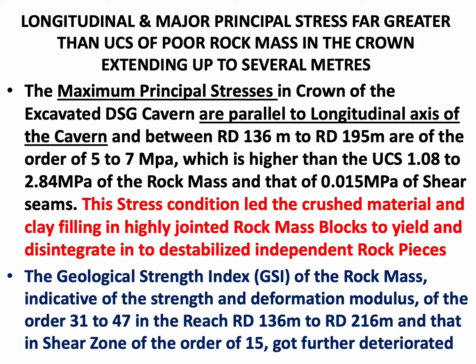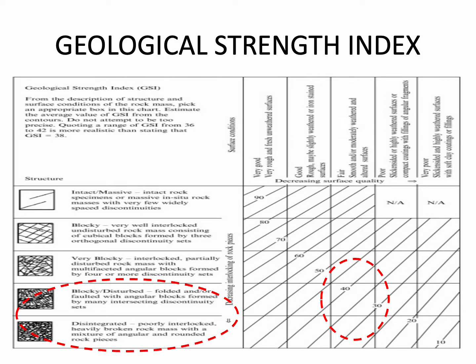The geological strength index of the rock mass, indicative of the strength and deformation modulus, is of the order of 31 to 47 in the reach 136 to 216 meter, and that in the shear zone of the order of 15 must have got further deteriorated. These are the original geological strength index considered, but with the stress conditions that we are seeing, of 5 to 7 MPa, which was much more than UCS of the rock mass, definitely the geological strength index would have come down further. The geological strength index falls in this reach, which represents blocky, disturbed rock mass, to disintegrated and poorly interlocked, heavily jointed, broken rock mass. It falls in this reach.